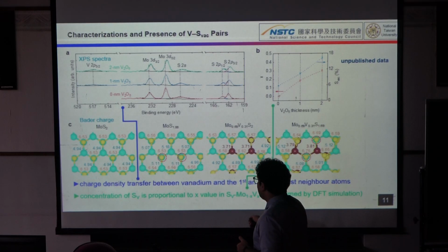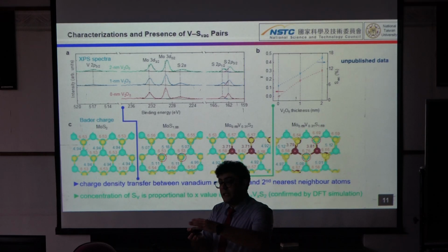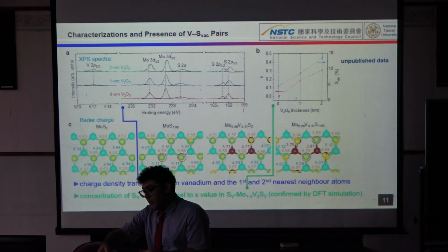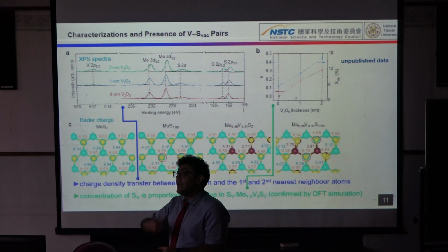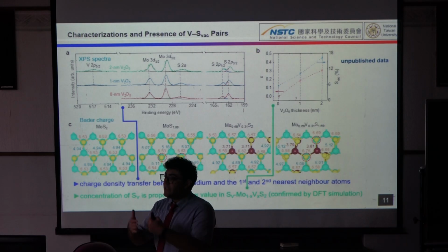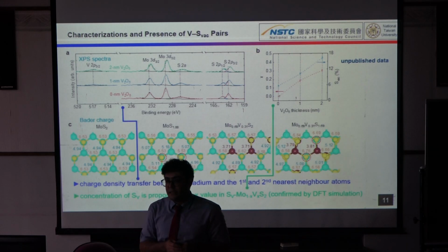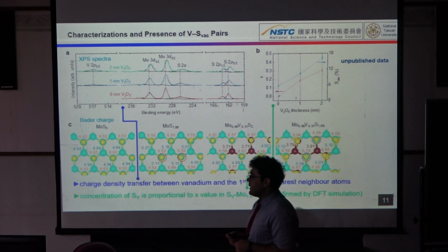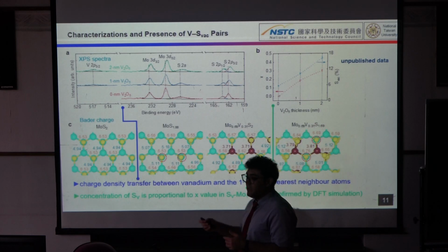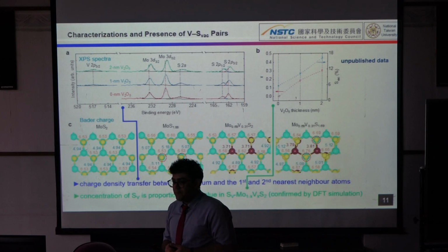So then you can make a lattice and calculate the formation energy. Then you take one of the sulfur out and again calculate the formation energy. Then the difference means the formation energy of sulfur that you can see there. Okay, I got it. So that should be negative, otherwise it's not the same. Yeah.